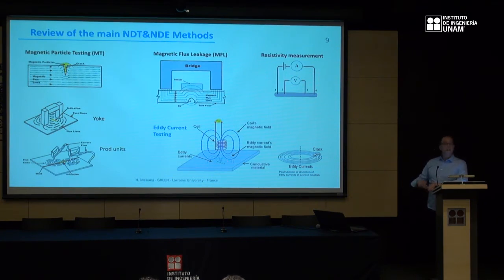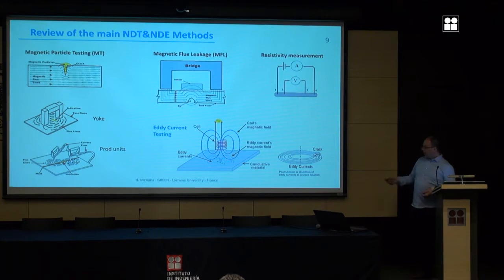These eddy currents will create their own field that will oppose the primary field, the source field created by the coil. That will result in a change of the impedance of the coil. This change of impedance will be used to characterize the electrical and geometrical properties of the tested material. Why? Because the eddy currents created in the material depend directly on the electrical conductivity, the permeability, and even the thickness of the material.